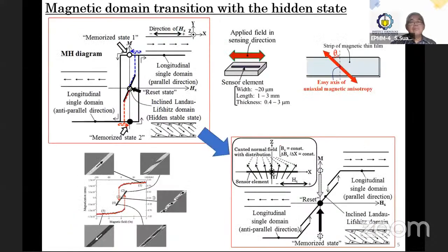Let me explain the physical details of this transition phenomenon. The upper left schematic shows the state diagram of this phenomenon. It is a magnetization diagram in which the horizontal axis represents the applied external field and the vertical axis represents the magnetization of the element. The applied field is a magnetic field along the length direction of the element. It's well known that a soft magnetic strip element having a needle-like shape is dominantly affected by the field along the length direction due to the demagnetizing force.